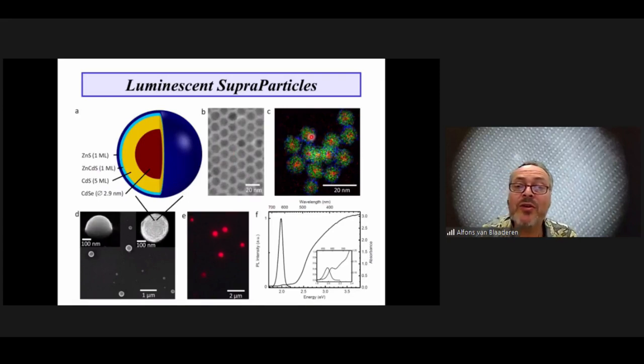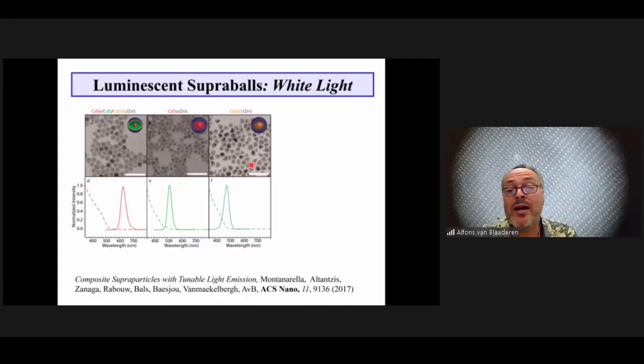So the very high quantum efficiency of this core-shell system, and here is EDX showing that it's indeed a core-shell structure, is such that when the particles are self-assembled in this particle of several hundred nanometers in size, the superparticle, it is therefore very strongly luminescent. It's still strongly luminescent because the quantum mechanical wave functions don't overlap. So why is this interesting?